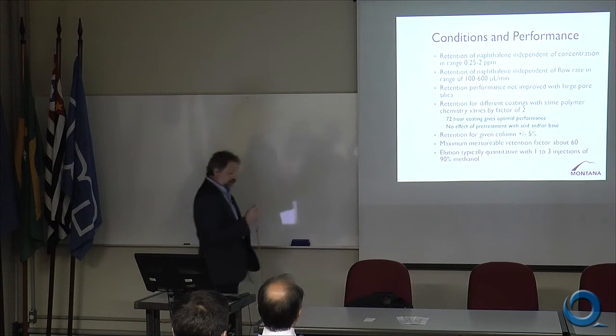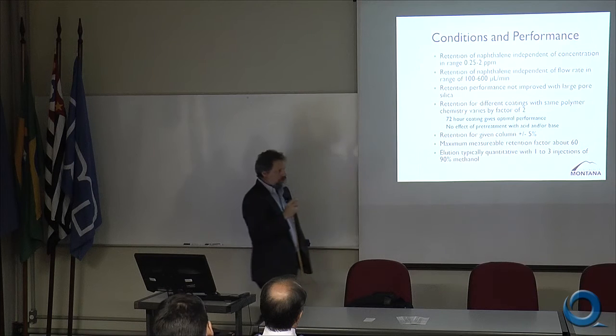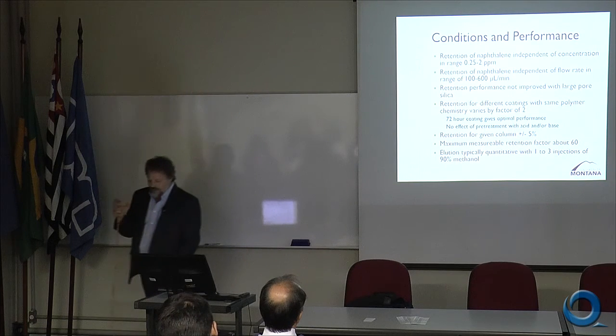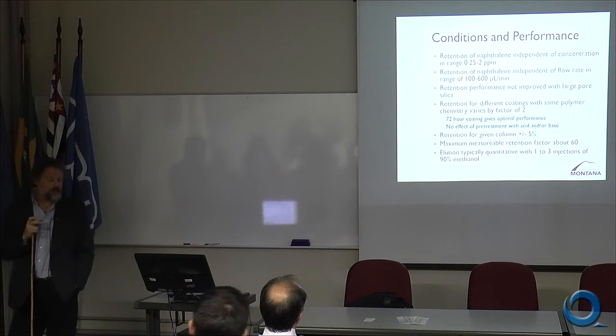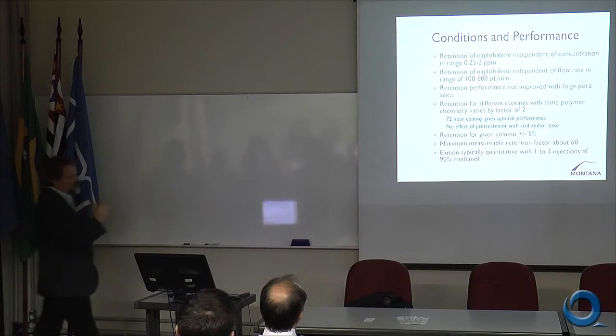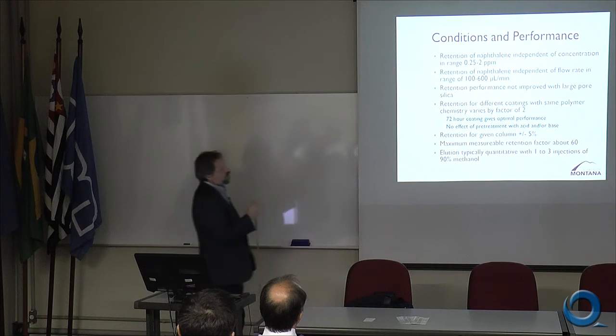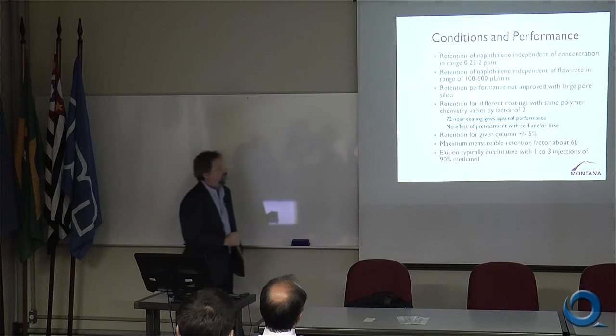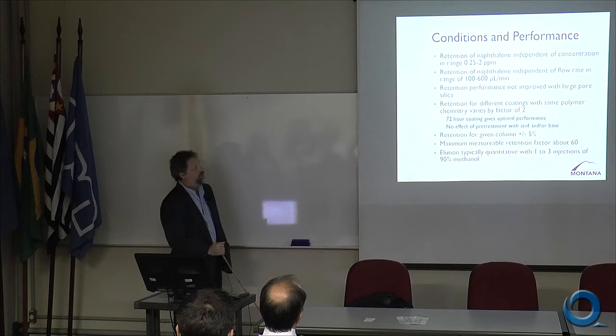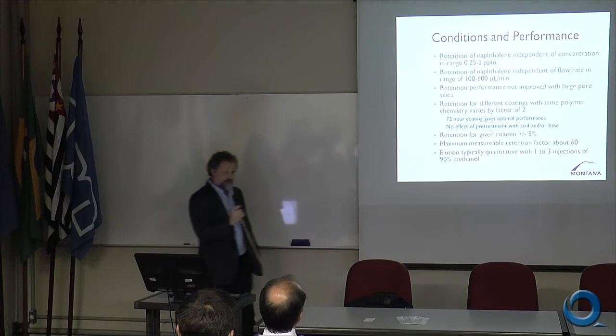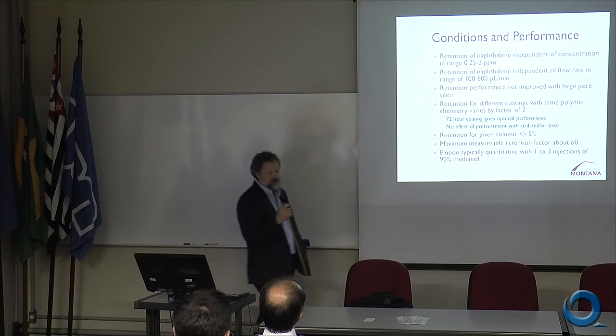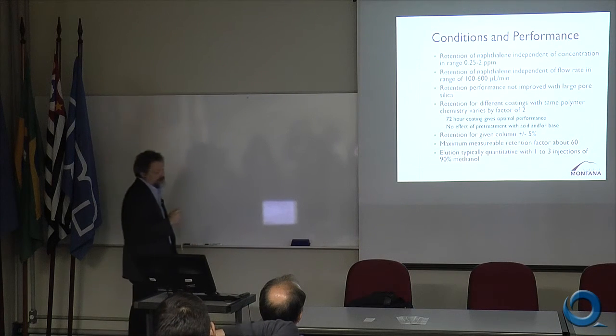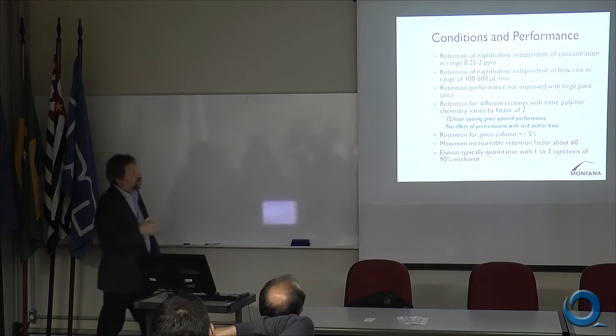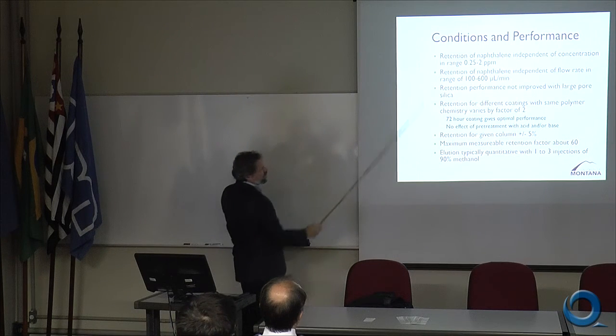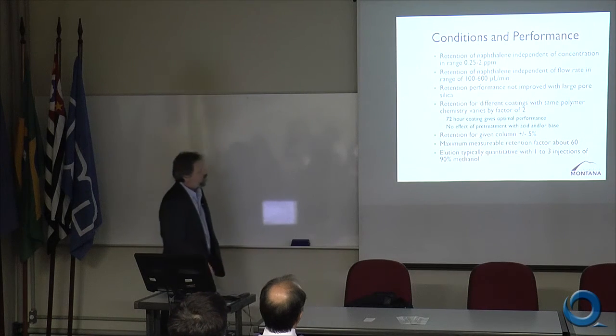We did try to use some large pore silica with larger pore size, to see if we could get more nanoparticles adsorbed down inside the pores. And performance was not at all improved with that material. So either because the material had lower surface area or because it really isn't an important effect, the large pore silica was not something that worked out for us.